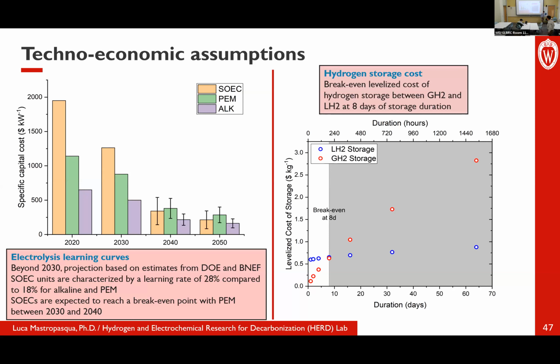To go along with that, some of the environmental implications of these systems: what is the feedstock as far as water? What's the requirement for the water feedstock? For high temperature electrolyzers, there are fewer requirements in terms of water purity. For low temperature electrolyzers, you need deionized water, so any water resource needs to be very much purified before feeding it to a low temperature electrolyzer. For high temperature, you can use tap water, but of course that degrades the electrolyzer faster.